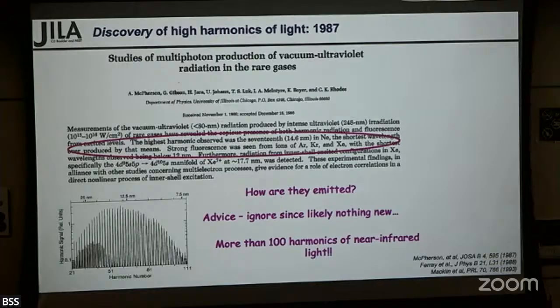But by 1993, people were seeing spectra like this. So this is seeing like 111 harmonics of the fundamental laser light with roughly equal intensity. And people knew immediately there must be some new physics because, for example, with harmonics of sound, you expect the higher harmonics to get weaker and weaker and weaker. This was clearly not going on here. And so, what was different in this experiment than the ones preceding?